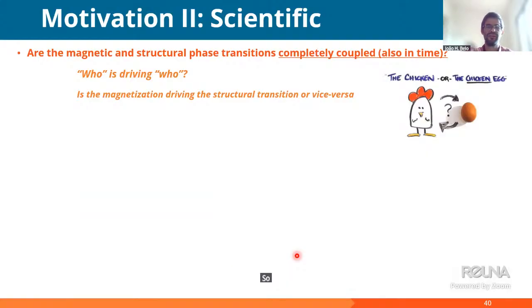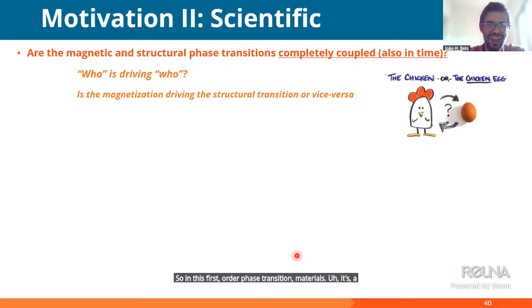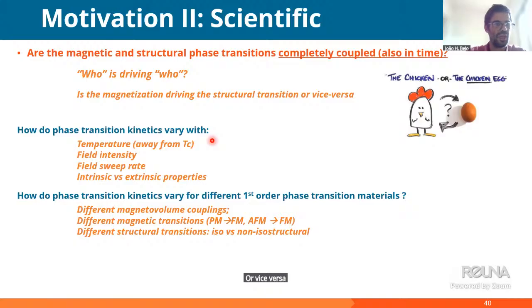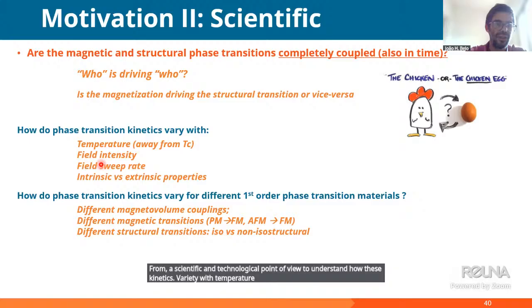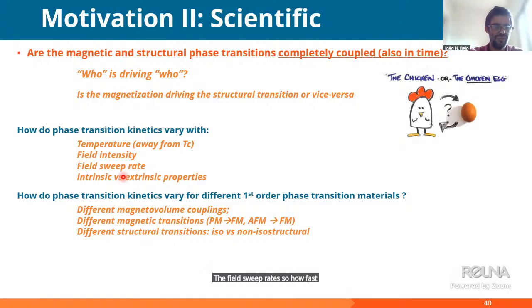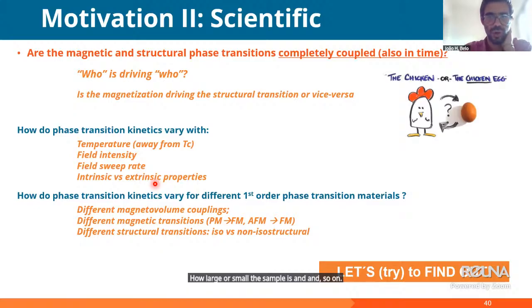So this leads me to the other motivation of this work, which is scientific. In these first order phase transition materials, it's a bit of a chicken and egg question of who is driving who. Is the magnetization driving the structural transition or vice versa? Also, it's very important from a scientific and technological point of view to understand how these kinetics vary with temperature, field intensity, the field sweep rate, so how fast we are changing the field, and also how it depends on the intrinsic but also extrinsic properties, such as the thermal environment of the sample, how large or small the sample is, and so on. So let's try to find out.